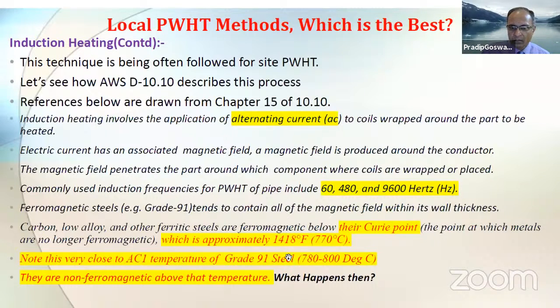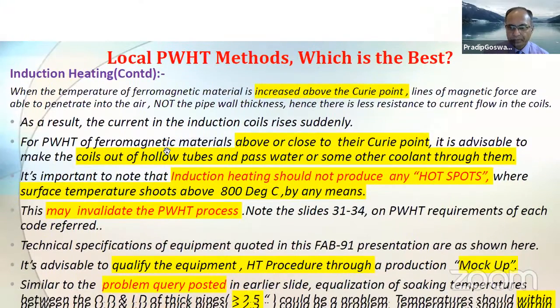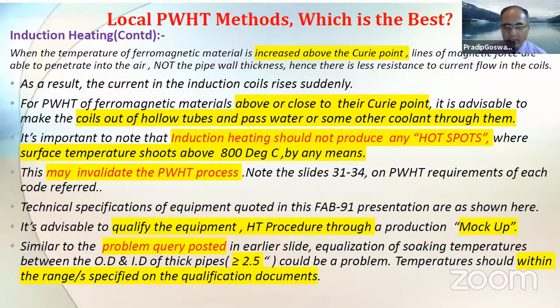But one problem area, or one of the drawbacks of this method, is this Curie point, where the alloy, P91, which is a ferromagnetic alloy, gradually turns non-magnetic when it is exposed above this temperature. But that doesn't mean that induction heating cannot be done. Induction heating is a popular heat treatment method, and it is adopted by the industry.